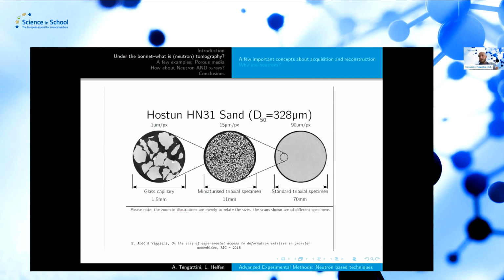And which one of the two is interesting? It really depends on your problem, because if you look at the sand at the level of a whole coast, well, you don't really care about the individual grains. But if you start trying to understand how the different grains interact together, well, you better have an image in which you can see the grains. And if you want to pass to the step after, trying to say, okay, maybe in some conditions these grains can break, for example, if you build a house on top of them, they would start breaking. Well, then you need a very high resolution. You need to focus on a much tinier area. So depending on your problem, you can study the same thing at different resolution, but resolution is not the only parameter. As you've seen, you might want to have more of them at lower resolution or fewer of them at much higher quality.